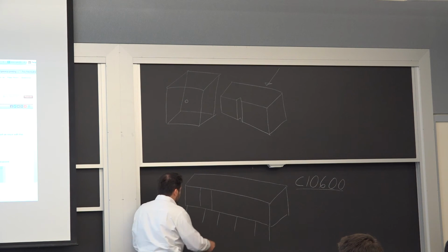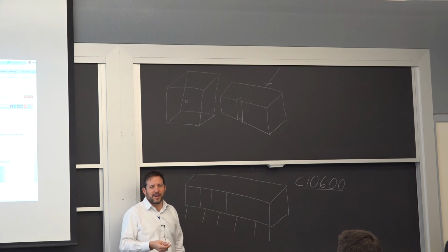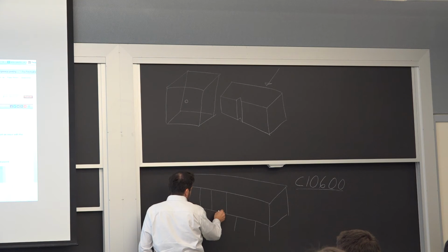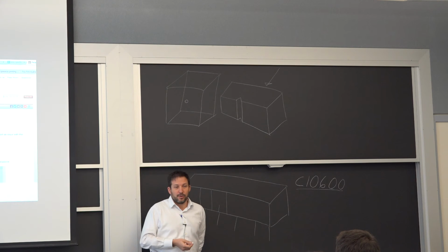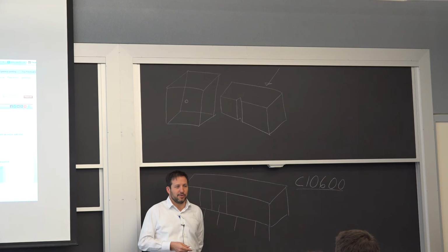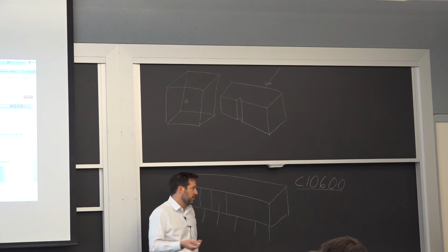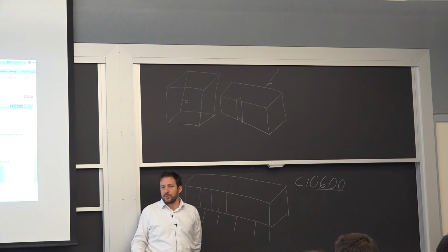So right after the first season, and that's really funny because you ask, so when did it crack? Oh, in the late fall, just before Christmas. That makes sense, when everything was trying to shrink but couldn't. So there was a first crack that started this way, and then they said, well, maybe that one panel was wrong. So they started trying to cut this up and make a new one. And then another crack started, and another crack. And soon they called for more experts, saying, what's going on here? Well, what's going on is you have a lot of stresses, and you have a brittle material.